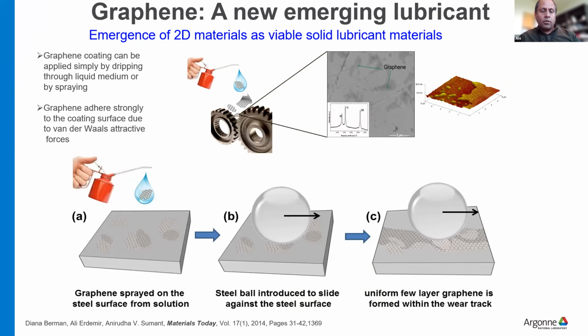So one can imagine that you can just disperse these graphene platelets through some solvent solution, maybe alcohol or ethanol, onto the stainless steel surface, and then there is an uneven distribution of these graphite or graphene platelets. Once you start rubbing the surfaces against each other, there is a self-assembly of this graphene onto the surface, because of very, very low shearing between these graphene layers. And then within the wear track, it provides a nice layer of graphene, and that reduces the friction and wear. So it works very differently than the traditional thin film solid lubricant coating, because they are stationary, whereas these flakes are mobile and act as a kind of crystalline oil, and provide better lubrication, and it changes as your surface changes. So that's the dynamic part of graphene as a lubricant.